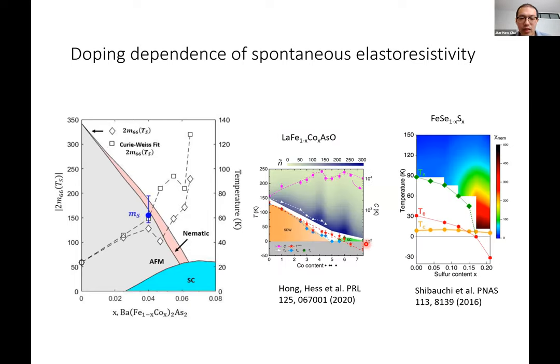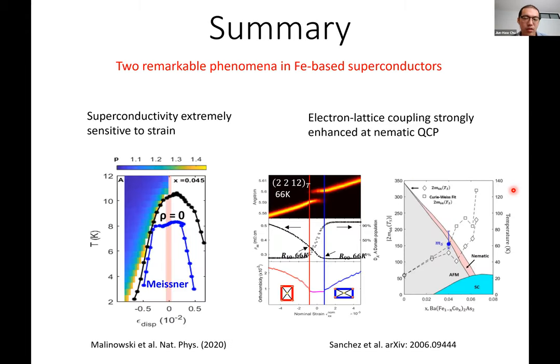So finally, I just want to say that in addition to the cobalt-doped barium 122, there are also nematic susceptibility measurements for other systems, for example, the 111 compounds and also the iron chalcogenides. And intriguingly, I think all the systems behave very similarly. You can see that the nematic susceptibility not just diverges as a function of temperature, but if you trace along this phase boundary, they also see enhancements as they go towards the quantum critical point. So this behavior could be a very generic phenomenon of a nematic quantum critical system. Okay, so I'll just leave my summary slide here, and I think this is the end of my talk, and I'll open for questions.